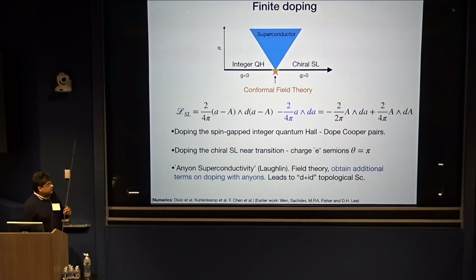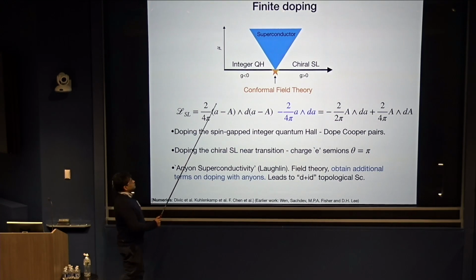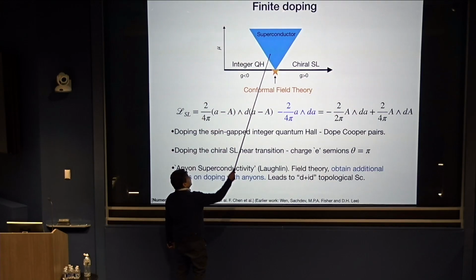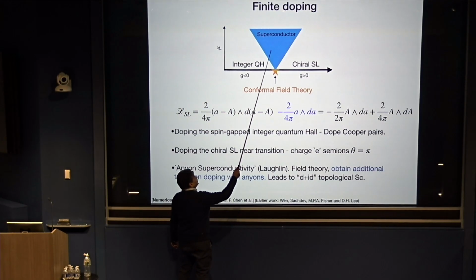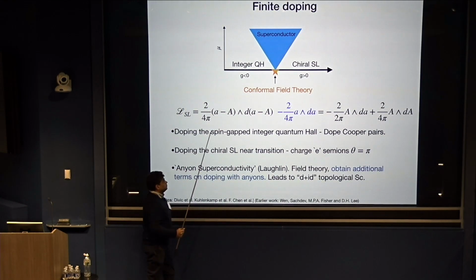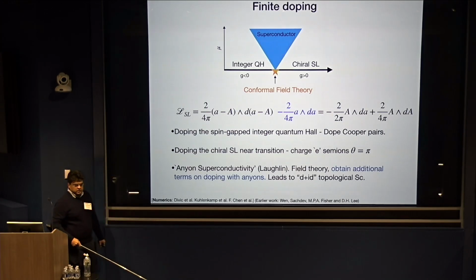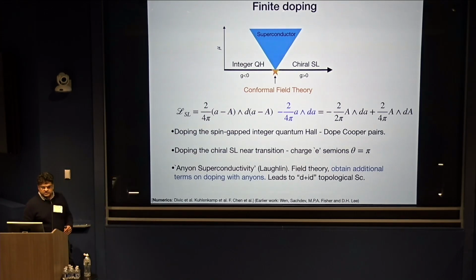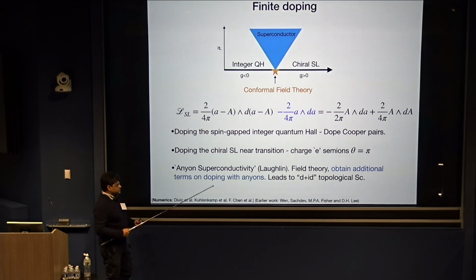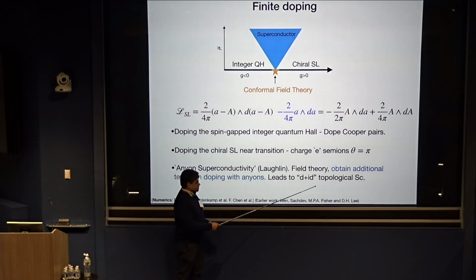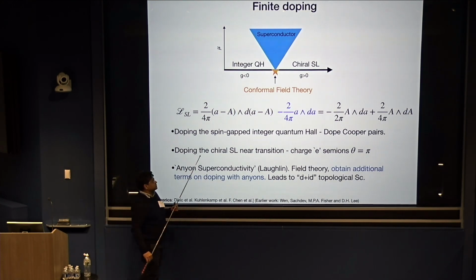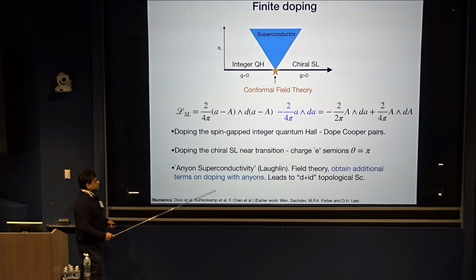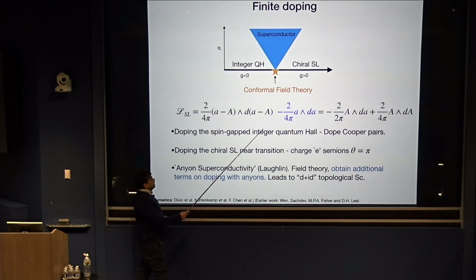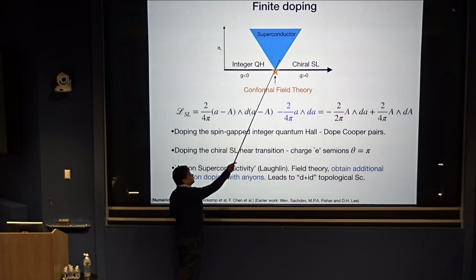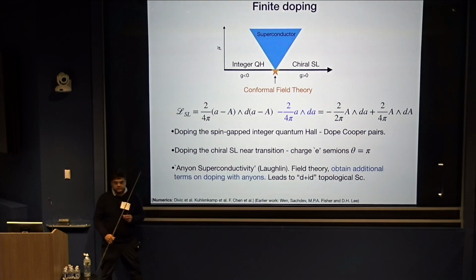This tells you that you get the same result if you go from this side or that side. You could have a single phase of superconductor. It's a conventional superconductor in the sense that it has no fractionalization, no exotic particles. It's unconventional in the sense it has edge states, but that's a mild version of unconventional in this context. But it's obtained by an unconventional mechanism, by doping these anyons and getting into the superconductor.